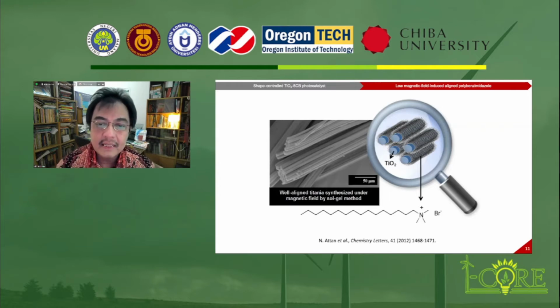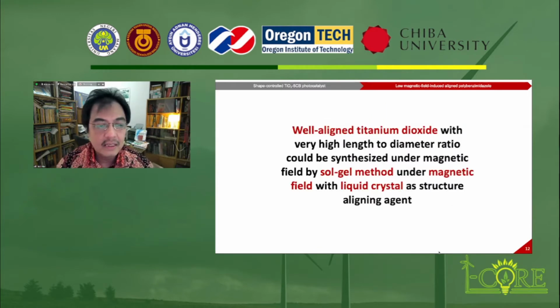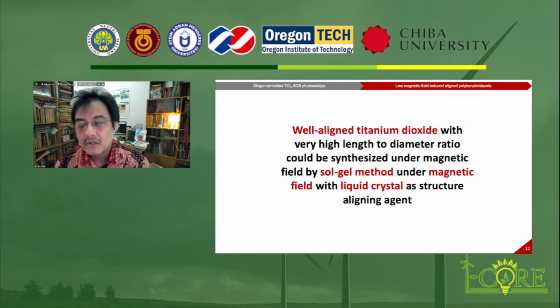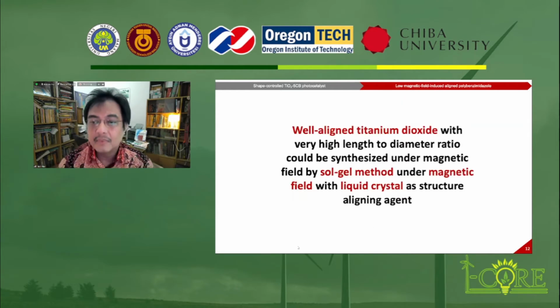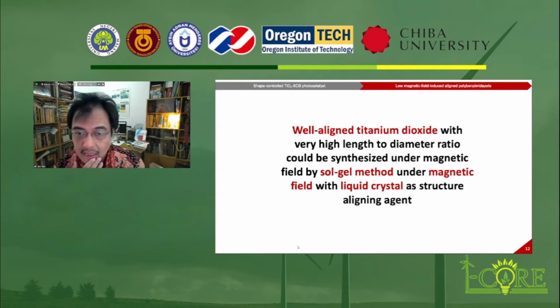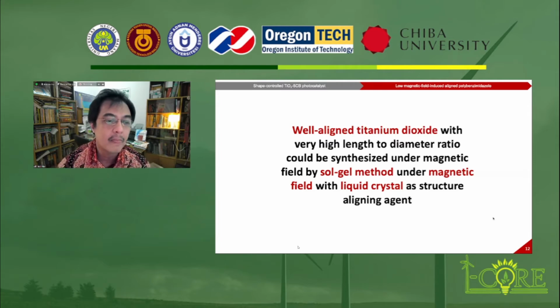We took the initiative of replacing CTABr as a structure directing agent with a material that has good magnetic properties, namely liquid crystal. Our hypothesis is that well-aligned titanium dioxide with a very high length to diameter ratio could be synthesized under magnetic field by the sol-gel method, with the liquid crystal as the structure aligning agent.